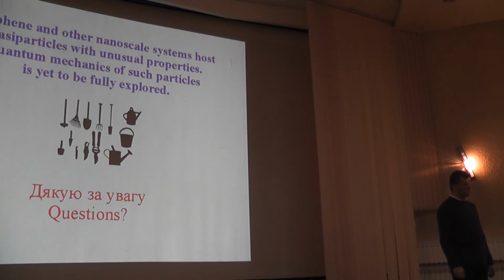Okay, and then just a short second half of the question. Can you explain in simple terms why there would be an increase of the local density of states expected should this collapsed quasi-atomic state take place? It happens because you have those collapsing orbits classically. Then you have to quantize them, say using the Bohr-Sommerfeld quantization rule, which says that an integer number of wavelengths should fit into these orbits. And that basically gives you the collapsing peak.